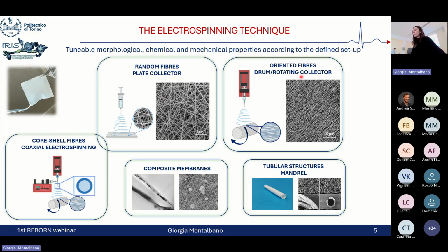So if we focus on the upper part of our slide, we can see how just changing the collector, we can in some way modulate the different orientation of the deposited fibers, where using a plate collector, we obtain randomly oriented fibrous matrices, while when we use a drum rotating collector, we favor the alignment of the deposited nanofibers. And also, if we even use a very small diameter drum collector, called mandrels, we can also reach the design of